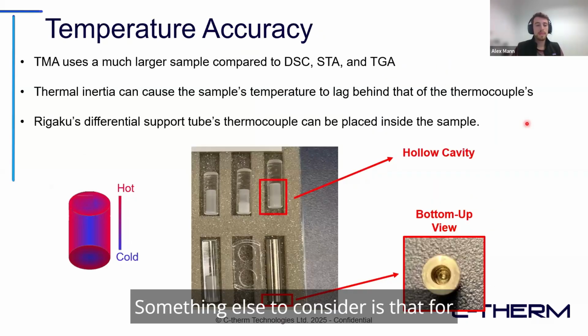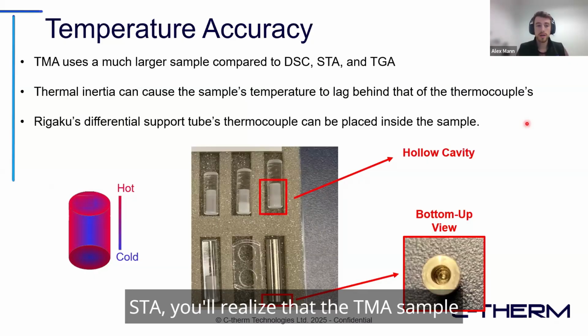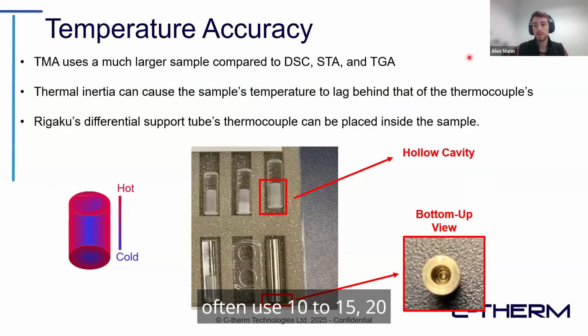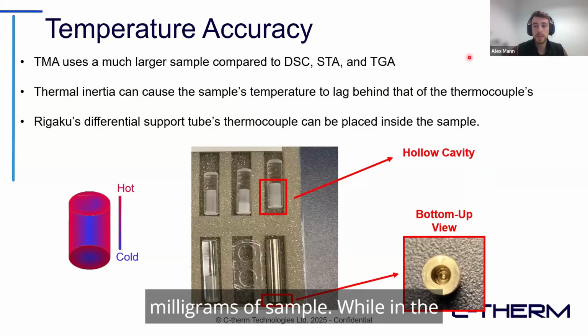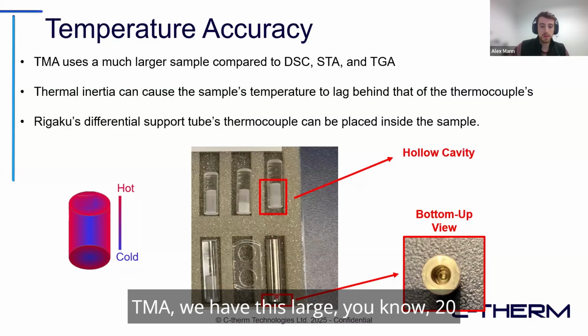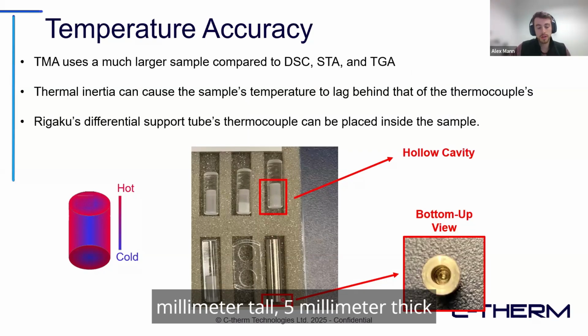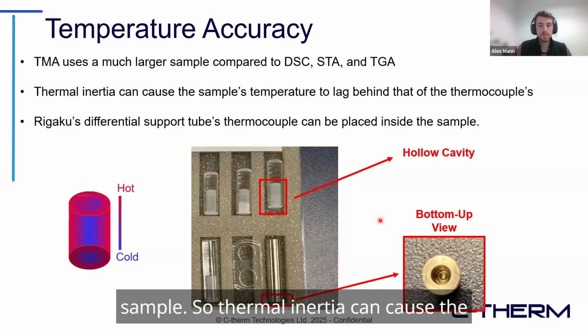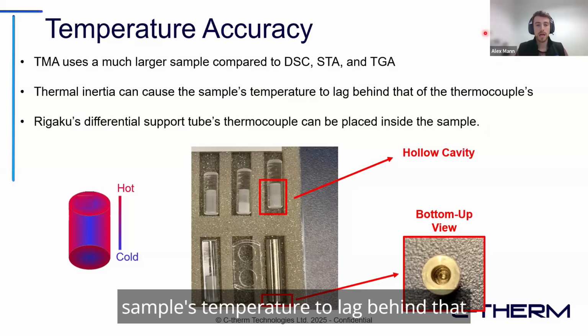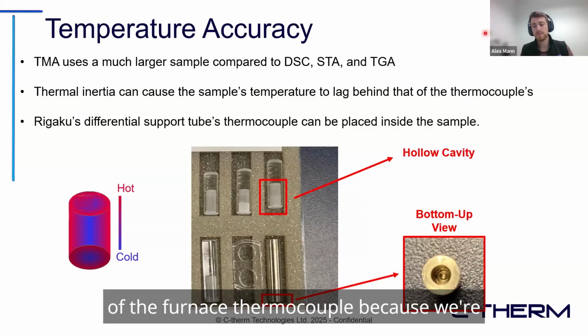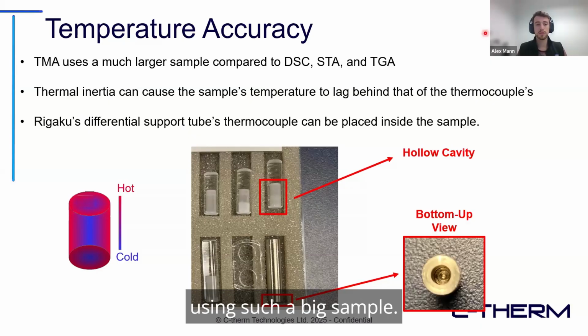Something else to consider is that for those who are familiar with DSC, TGA, STA, you'll realize that the TMA sample is much, much bigger. So when you're using these other methods, you'll often use 10 to 15, 20 milligrams of sample. While in the TMA, we have this large, 20 millimeter tall, 5 millimeter thick sample. So thermal inertia can cause the sample's temperature to lag behind that of the furnace thermocouple because we're using such a big sample.